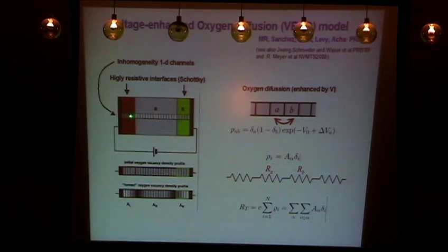So each vacancy that you put on the interfaces will produce a relatively much higher contribution to the two-terminal resistivity. Here we have other parameters, AL and AR, which for simplicity we're going to take for a moment to be equal, and which are much larger than 1. So then you just have in the model a simple one-dimensional resistive network where each one of these resistors depends on the oxygen concentration. So you're going to have a landscape of resistance.